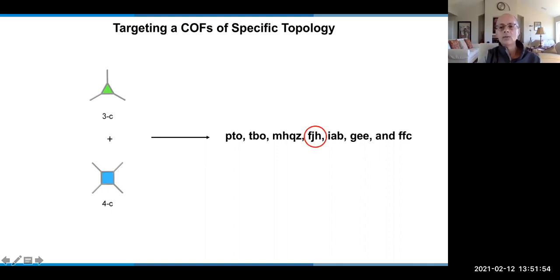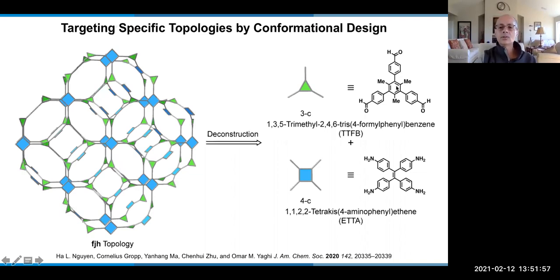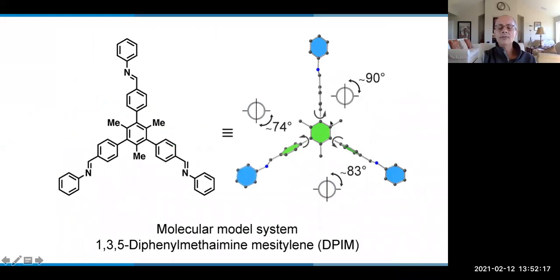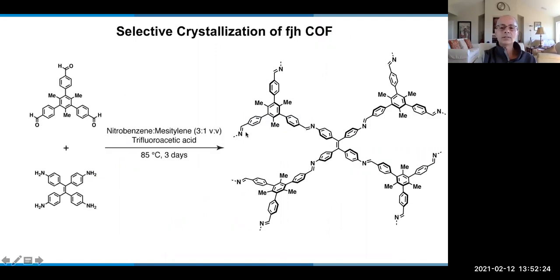Okay, so again, we use what we know from organic chemistry, which is that linkers of this kind. So basically you take the topology, you dissect the topology and you look at the angles and say, well, I need to be able to turn these aldehyde with respect to each other. So I need this stereochemistry where the methyls allow you to have these particular angles, okay? So that you can make that particular topology by putting the methyls here and controlling the conformation of the building unit, and therefore be able to achieve that topology among the other topologies.